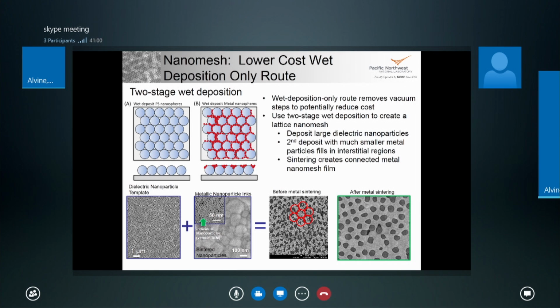So what we can do is make everything with wet deposition by using sinterable metallic nanoparticles. We start off with a template monolayer, this time of silica particles, so they're thermally robust. Then we come in with a much smaller silver nanoparticle, and by wet deposition and controlling the wetting and capillary forces on the surface, we can controllably place the metal nanoparticles into the interstitial regions of the larger spheres, as shown here.